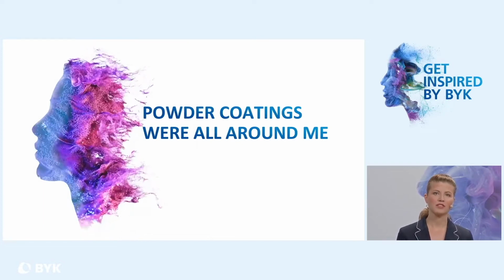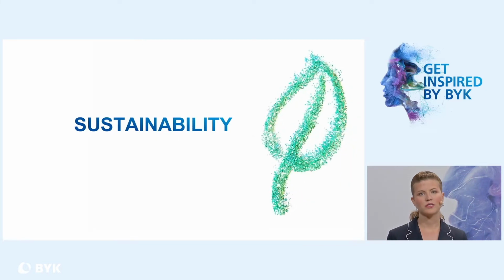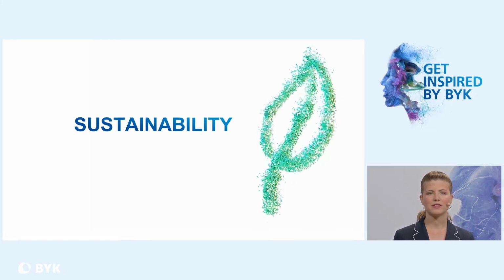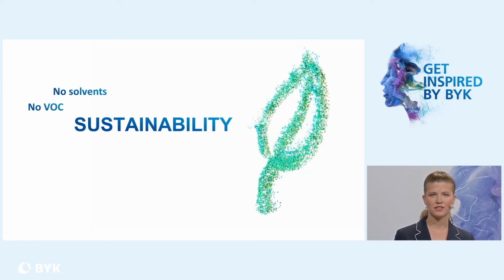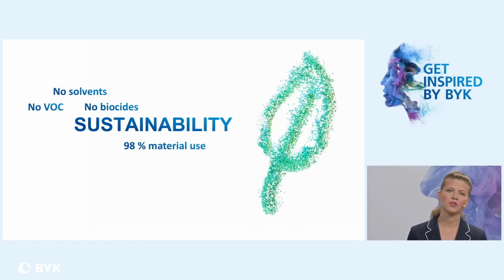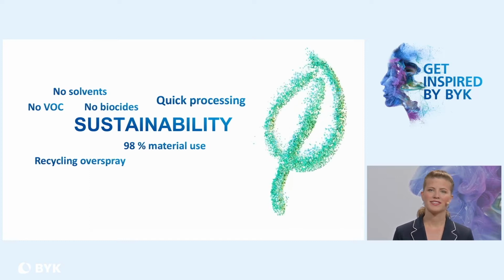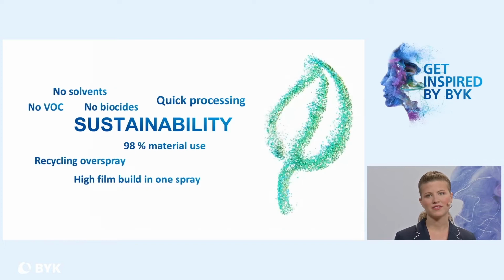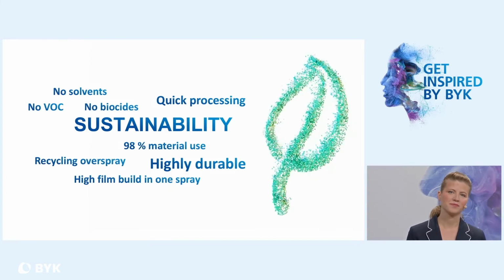Powder coatings are sustainable. Facing climate change, powder coatings can be one step towards more sustainability in the paint industry. In this technology, we don't have any solvents, there are no VOCs, there are no biocides needed. 98% of the material can be used. The overspray can be recycled. We have a quick processing without the drying steps, and we have a high film build in just one spray. We create highly durable systems to protect what is valuable to us.